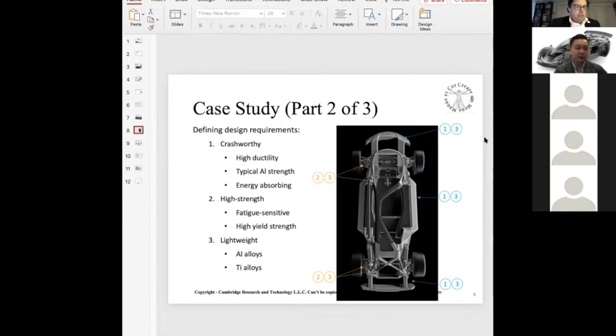Like many other automotive companies, we also invest in triaxiality programs, truly understanding the stress state of the material at a high strain rate. And then we create a material card so our structures team can use it in their FEA analysis. I mentioned the control arms and the A pillars and B pillars. Those are very fatigue sensitive and high strength components. So with these two big topics, we go back, open our books, and engineer a truly 3D printable aluminum alloy that can meet these requirements.